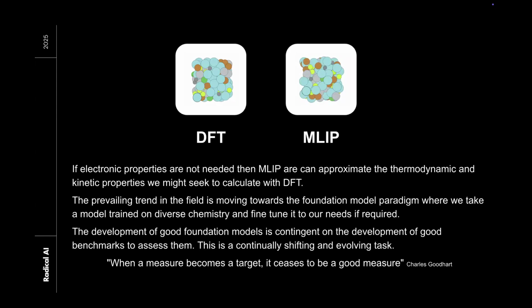And so the question is, in a space of alloys where there is limited alloy DFT data, or at least limited large-scale alloy DFT data, because the alloys that we're studying are disordered, which means that you need to sample many, many quasi-random structures to get a good understanding of the alloy. And in general, they have many more valence electrons that you need to consider because of the position of the elements in the D block. We have a problem with knowing which is the best model to use.